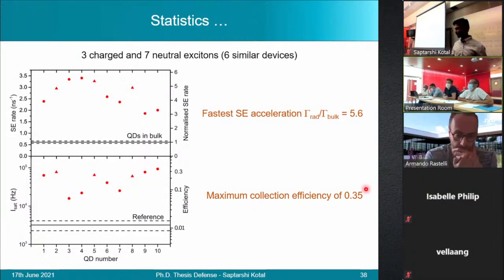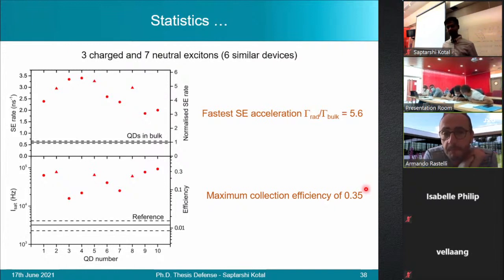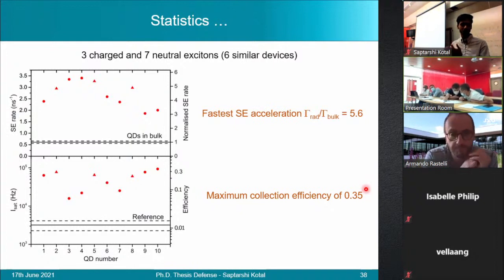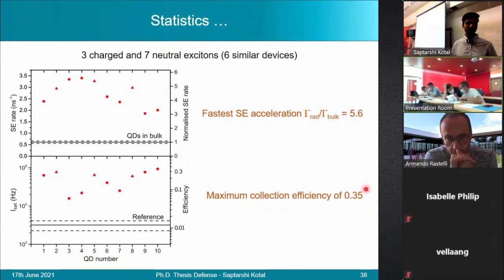Yes. So in this case, we think that this might be because the dot is actually spending some of its time in a charged state. Therefore, it's not always in the neutral state, and we lose some collection. I mean, we lose on the collection efficiency while still having a fast radiative recombination.